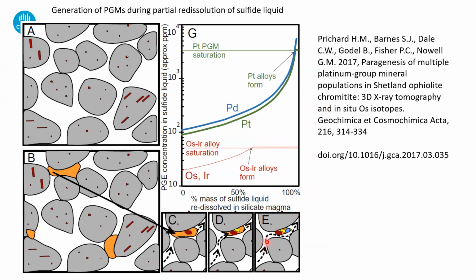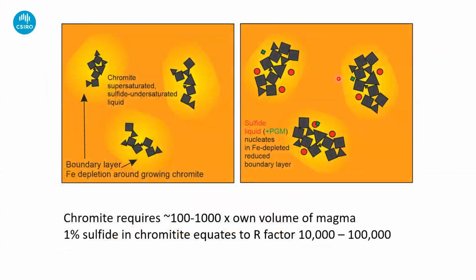So what we think we're seeing here is the result of initial growth of sulfide, probably also within a boundary layer around growing chromite grains, possibly due to local iron depletion or redox changes or whatever it is, something or other causing sulfide to nucleate immediately within the vicinity of the growing chromite grains. Now, here's an interesting point. If we're growing chromite from a magma, we know that chromite requires of the order of 100 to 1,000 times its own volume of magma to grow. That's just the concentration factor between a silicate melt and chromite.